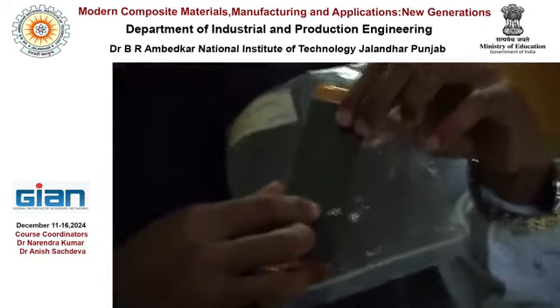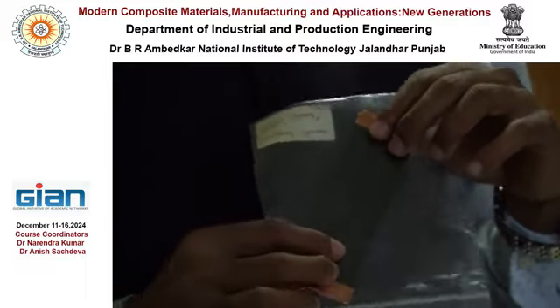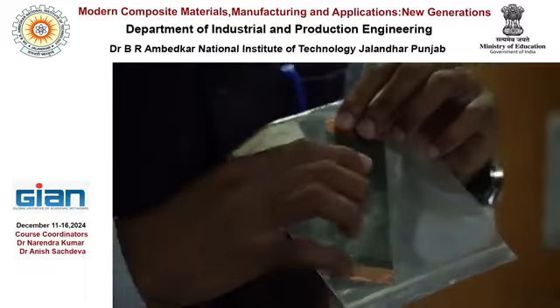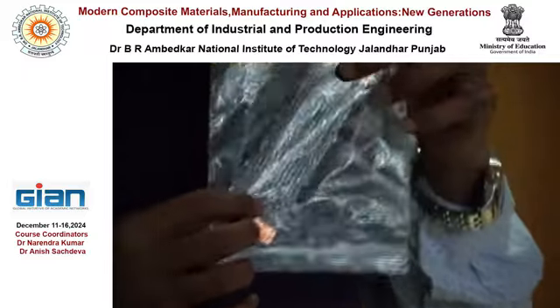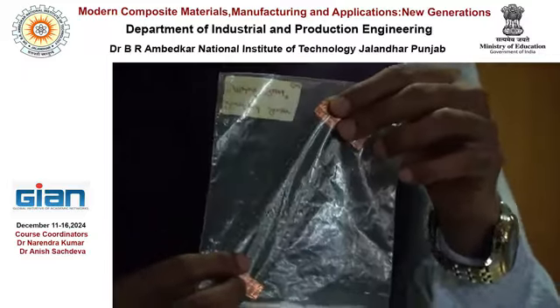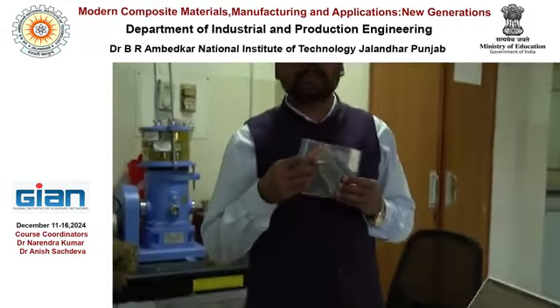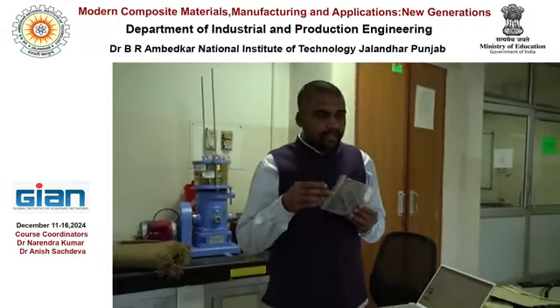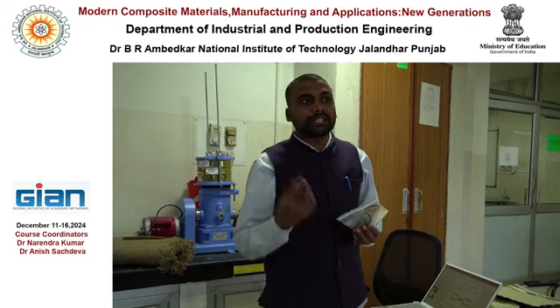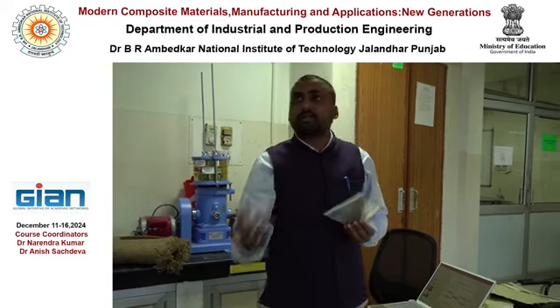And since we know graphene based materials are conductive in nature, this material will become a sensor, and we embed this sensor in the composite materials and try to measure the change in the resistance under the deformation.